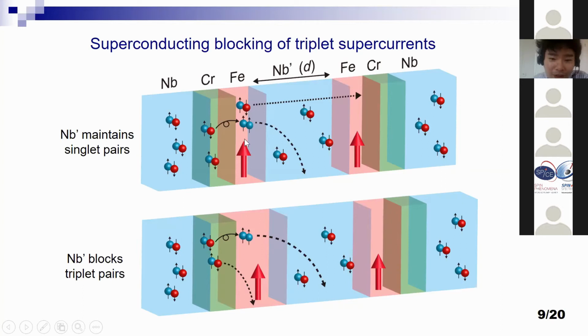And if we prepare very thin iron layers, then singlet supercurrent can penetrate through this device as well. And in this case, if singlet supercurrents flow through this device, usually supercurrent doesn't decay in a superconductor. So, for example, even if we increase the thickness of this superconducting barrier, singlet supercurrent shouldn't show a decay. But if we increase the thickness of iron and block the singlet component, then we can extract the behavior of pure triplet supercurrents.